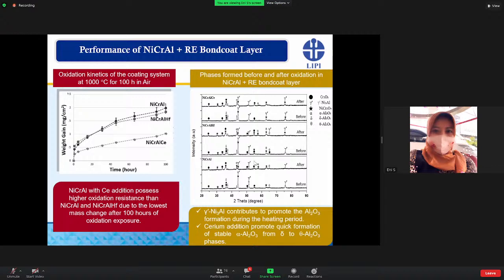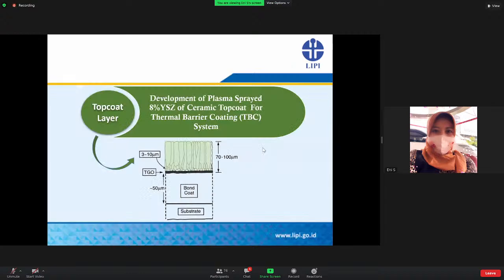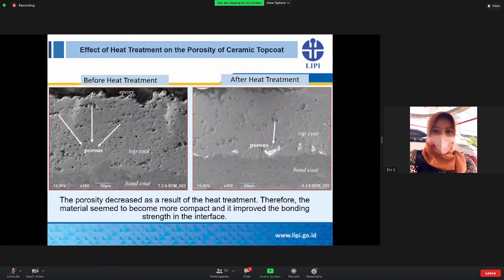Therefore, we would like to continue by depositing 8% yttria stabilized zirconia ceramic coating as a top coat layer for developing an excellent TBC system. This is a study to understand the effect of heat treatment on the porosity of the ceramic top coat. So we heat treated the sample at a temperature of 1100 degrees C. As you can see in these figures, the porosity decreased as a result of the heat treatment. Therefore, the material seems to be more compact, improving the bonding strength at the interface.